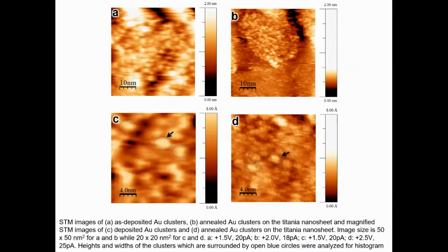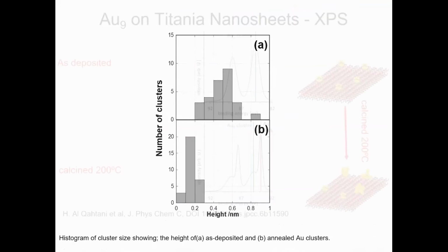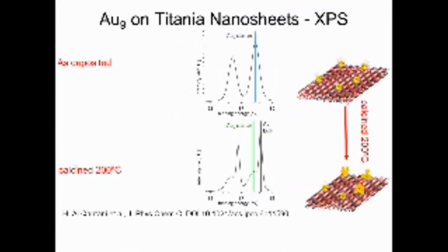And this is a close imaging of a single nanocluster deposited on the nanosheet using the STM itself. We create a histogram from it, and we saw the size has been reduced, and this is related to the removal of the ligands from the nanocluster. We also tried using XPS before and after annealing to show the degree of aggregation.